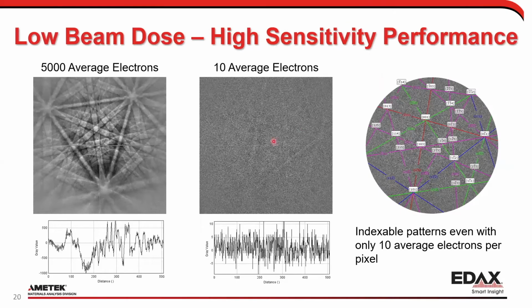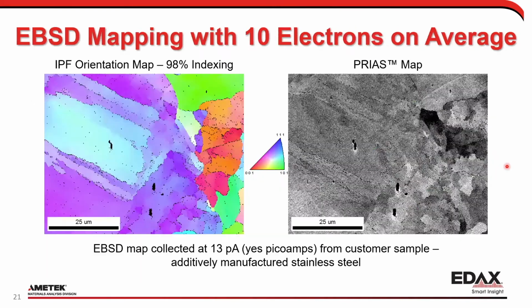On the left over here, we have 5,000 electrons per pixel on average. Over here on the right, we actually have 10 electrons per pixel on average, and that's on average here, so this is above background. You're only looking at maybe 7 to 8 electrons over background, and that is actually a perfectly indexable pattern as well. Here you can see it is indexed, and you can see this is mappable. This is 10 electrons per pixel at 13 picoamps of beam current on an additively manufactured steel.